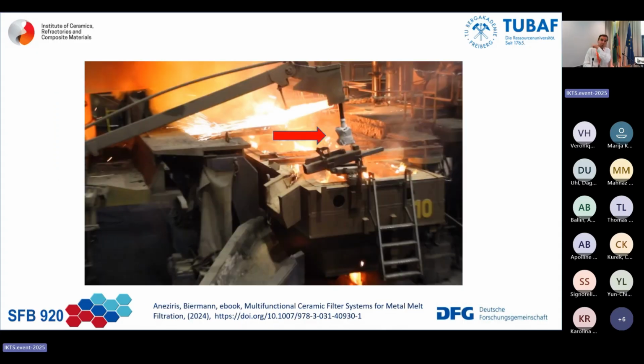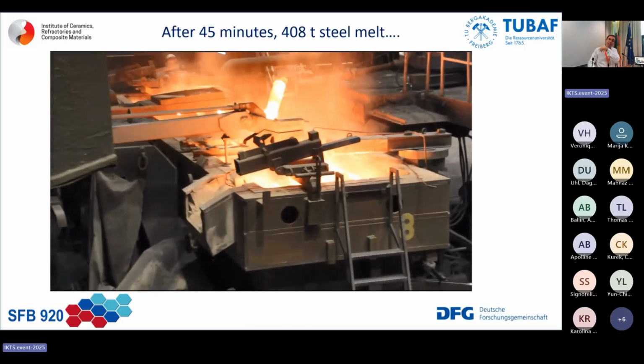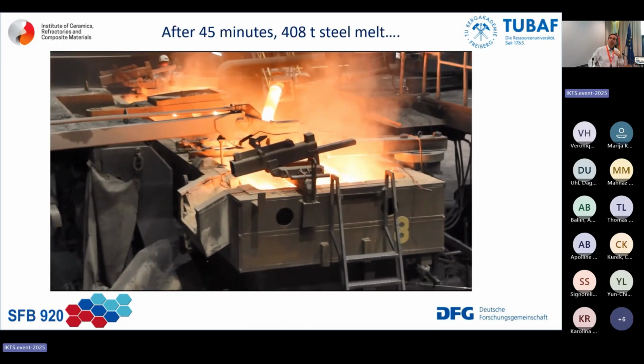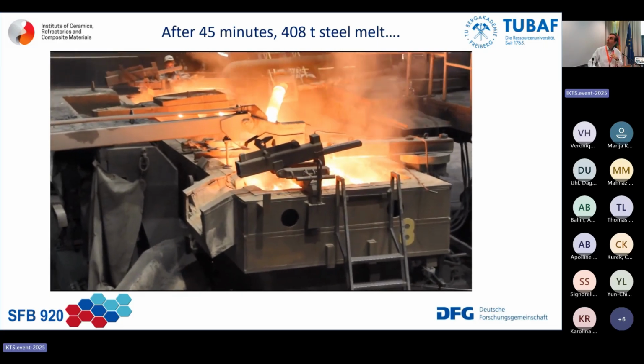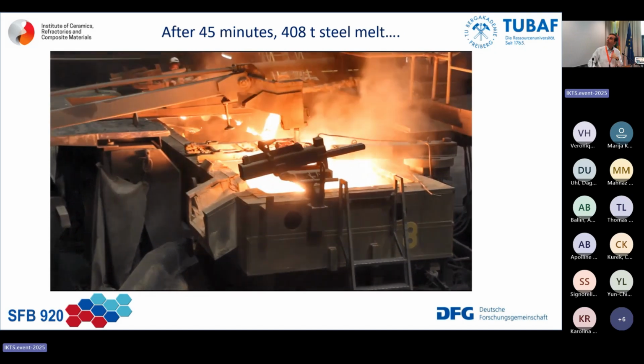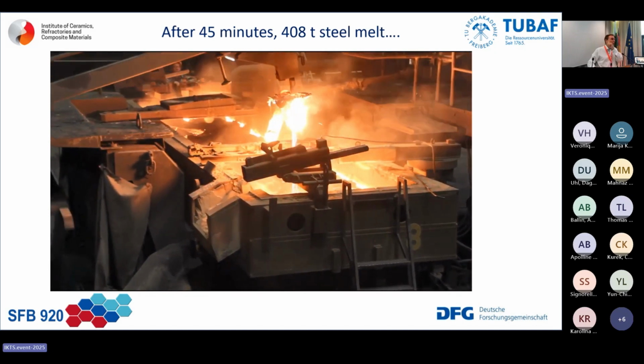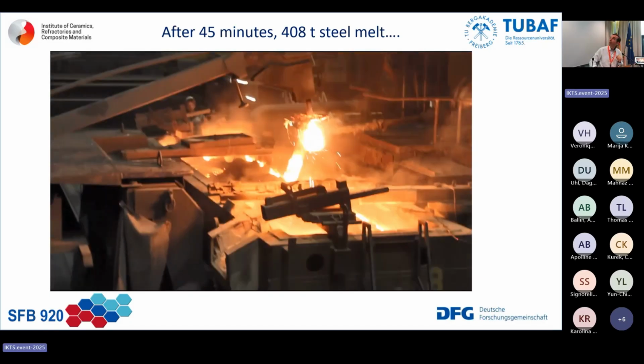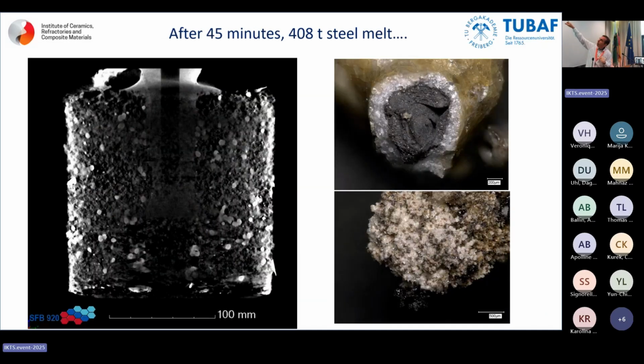So this was the filter package so that we can go via the slag line and not destroy the slag line. So we want to collect inclusions. The steel plant, I only will show when it comes up. And it survived because the deposits, that means the inclusions, sealed the carbon bonded alumina. So you can use the chemistry in order to improve the performance of your component. The bad things, combined for the good things.